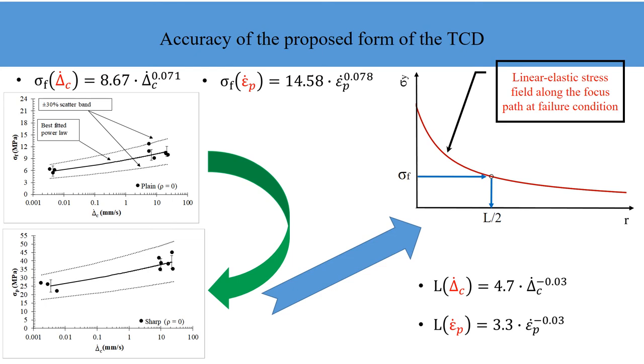The results of the unnotched specimens allow calibration of the constants describing material strength using the standard least squares method, both as a function of local displacement rate and maximum opening strain rate. Using results of sharp notched specimens tested under mode 1, at a given displacement rate the unnotched specimen results serve as an input to the generated linear elastic stress field along the focus path at failure. Using the point method, L/2 can be determined, and by repeating this process, the constants describing the material critical distance can be calibrated.